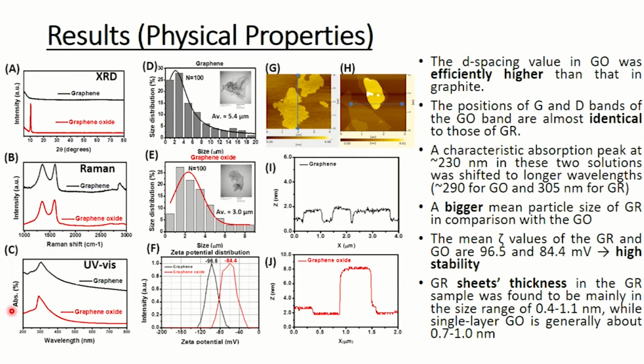So next, by UV-visible spectrum between graphene and graphene oxide nanoparticle solutions, we found that a characteristic absorption peak at around 230 nanometers was shifted to longer wavelengths in these two solutions, which is 290 for graphene oxide and 305 for graphene, suggesting extended pi-stacking interlayer conjugation. Furthermore, we also checked the size distributions and transmission electron microscope images of graphene and graphene oxide nanoparticles. Later we found a bigger mean particle size of graphene in comparison with graphene oxide. Furthermore, in the case of zeta potentials, we found that the mean zeta values of graphene and graphene oxide are 96.5 and 84.4 millivolts, suggesting the high stability of both dispersions.